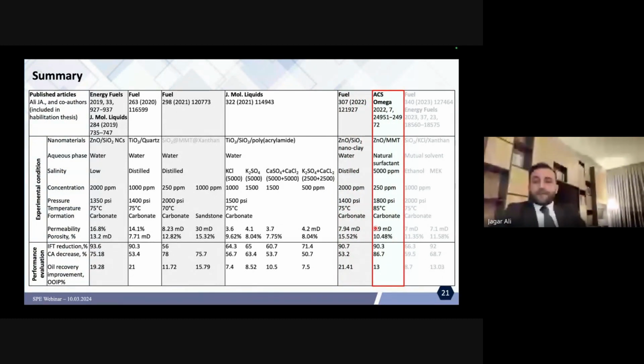When we mixed with natural surfactant, even though the contact angle reduction or wettability alteration is very high, and IFT reduction is very high, the core flooding oil recovery factor is not too high. So this needs more studies when we use the nanocomposite with natural surfactant.